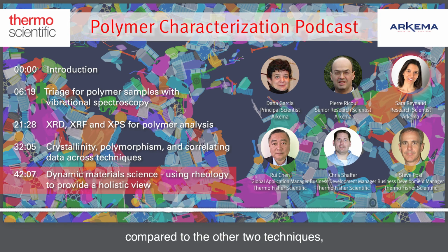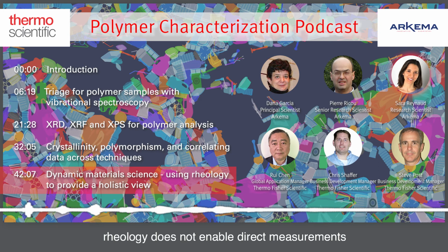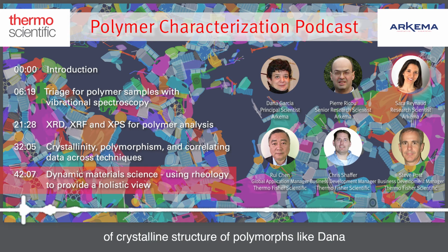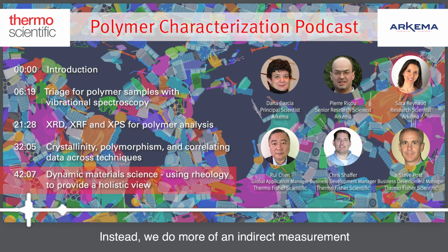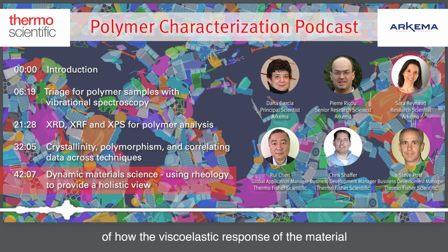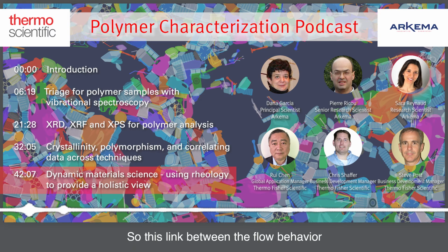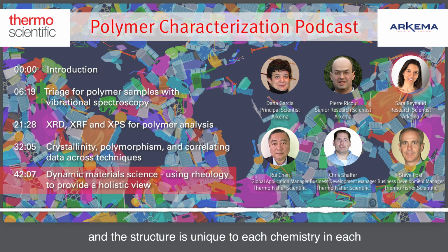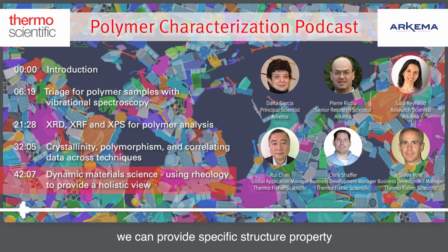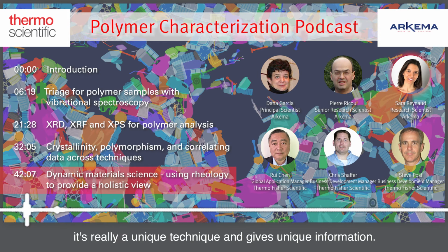So back to your question, compared to the other two techniques, rheometry doesn't enable a direct measurement of crystallinity structure or polymorphs, as Dana and Pierre were describing. Instead, we do more of an indirect measurement of how the viscoelastic response of the material changes due to the polymer structure. So this link between the flow behavior and the structure is unique to each chemistry and each polymer. In that regard, we can provide specific structure-property-performance information that can help in identifying processing windows and predicting optimal conditions for production. So I think it's a really unique technique and gives unique information.